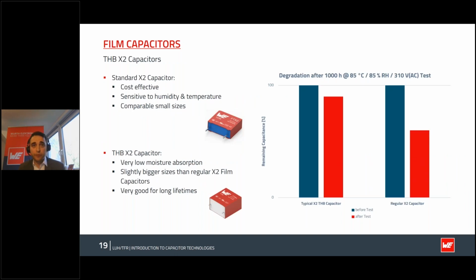As I mentioned, they are somewhat sensitive when it comes to humidity, and we protect them with an epoxide, but the epoxide is somewhat vulnerable when it comes to temperature variations. So we have the standard X2 capacitor, which is very cost effective and available in small sizes. But if you do want longevity for this part, you can switch to THB types, which you can see on the bottom. They are a little bit bigger, but they have a much longer lifetime, as they protect much better against humidity and temperature changes.